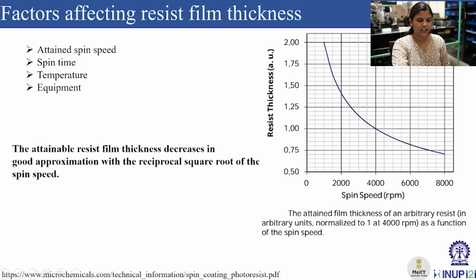While developing structures like microarrays and micropillars, the thickness of the resist film can actually affect the height attained. So we need to look at the parameters which can control the film thickness. These parameters are spin speed, spin time, temperature, and equipment. From this diagram, we can see as the spin speed increases, the centrifugal force increases, and hence the resist thickness that could be attained actually decreases. Same happens with the spin time. If the spin time is more, in that case the resist thickness will be less.